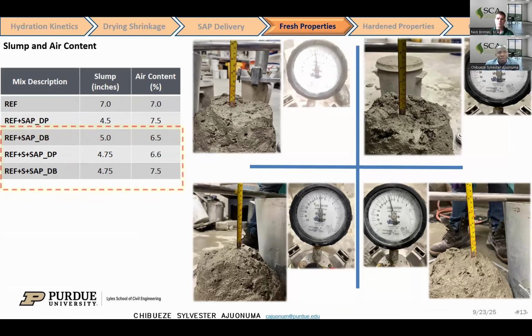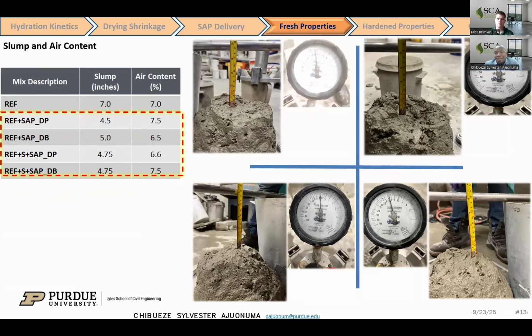Here we had the result for the fresh properties, where we tested the slump and the air contents. If you see here, we found out that the addition of SAP reduces the slump of the concrete, but we also found out that there was a comparable result both in air content and the slump, both for the addition of SAP using the dissolvable bag and directly pouring the SAP, showing the effectiveness of addition of SAP using dissolvable bag.